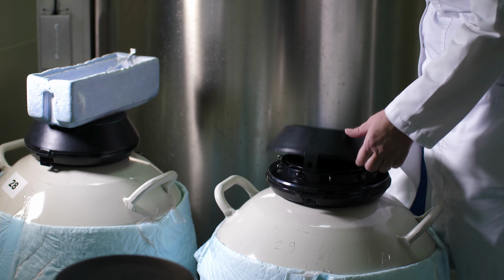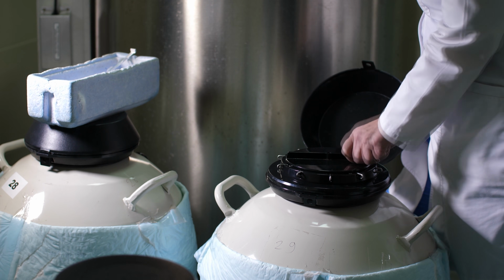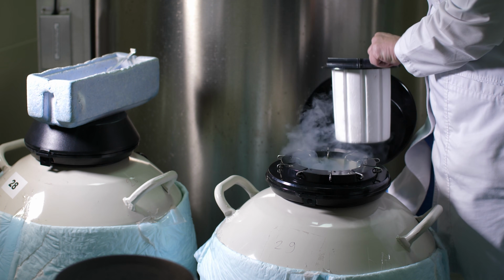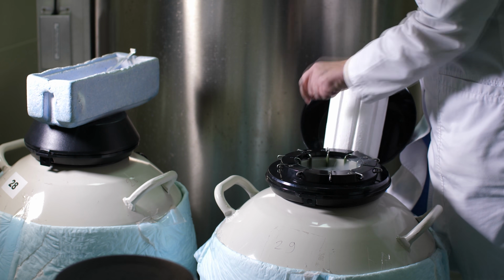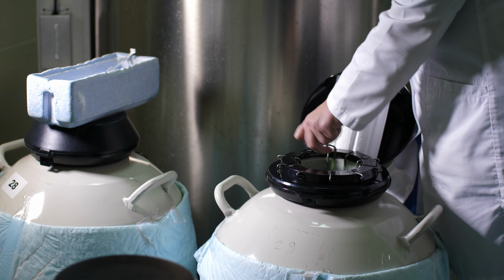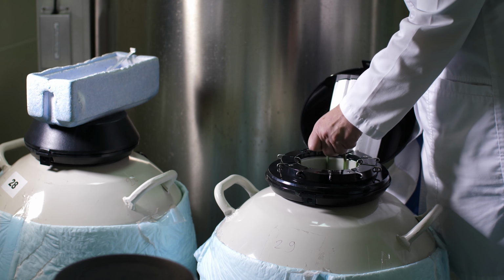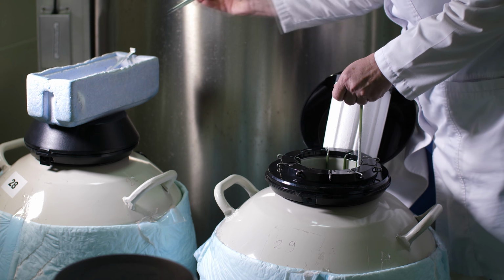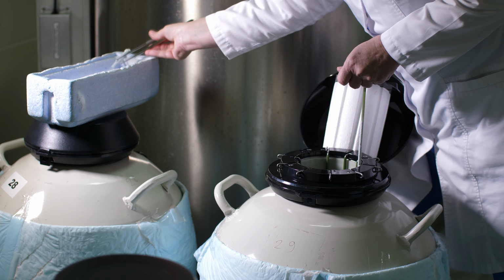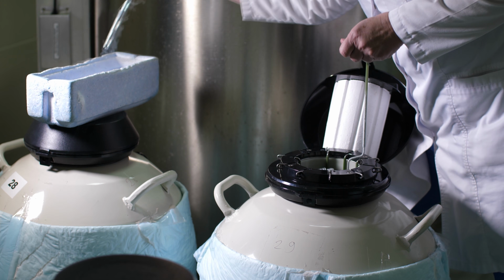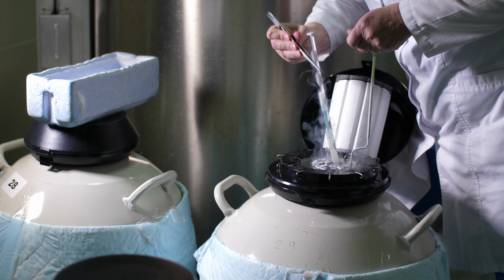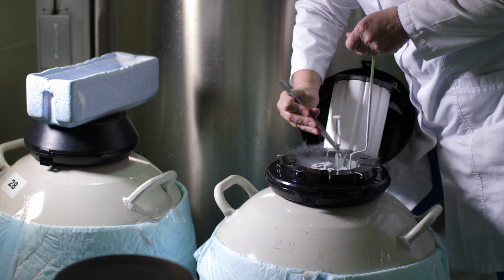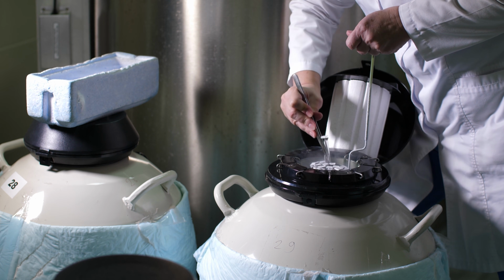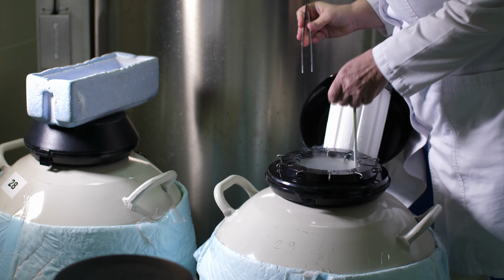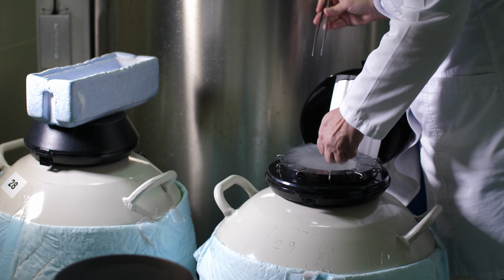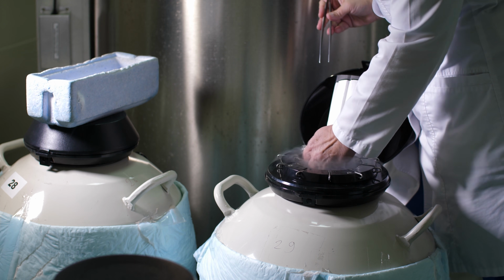Liquid nitrogen also shows a material embrittlement effect. Many materials contract significantly at that temperature. For some polymers and rubbers, the contraction is uneven or too rapid, and it causes them to shatter or crack when stressed. Also, liquid nitrogen is inert. It doesn't support combustion, and this remains true whether it warms from the liquid state or not. And this has led to documented industrial accidents when nitrogen displaces oxygen in enclosed spaces. Workers entering poorly ventilated areas have collapsed due to oxygen deficiencies.